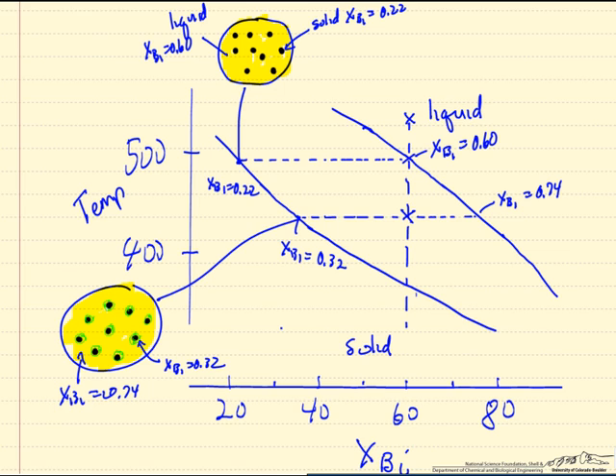This means since we have solid with a mole fraction of 0.22 and solid with a mole fraction of 0.32, the average is somewhere in between. This is a volume average, so it's certainly closer to 0.32. So our non-equilibrium overall composition of the solid is somewhere lower than this equilibrium line because it's some average of these values of the different solids that form.